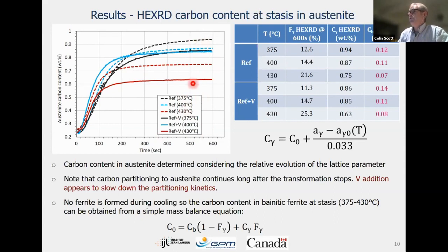And there is something quite interesting to do with vanadium. If we look at the dotted curves here, when you don't have vanadium, the retained austenite seems to achieve a higher end carbon composition, slightly. It's not huge, but there is a systematic increase in the carbon at the end of the transformation when vanadium is not present. When vanadium is present, we have less. So what we say from that is the vanadium addition seems to slow down the partitioning kinetics.